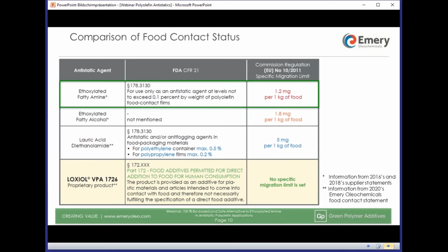An example. Let us assume you use 1 gram of packaging material to pack 1 kg of food, which is not much. Let us further assume you put 0.1% of ethoxylated fatty amine in the film, as allowed by FDA. Then you have 1 milligram of additive per 1 kg of food. If you assume worst case, which is full migration of additive from the film into the food, you are rather close to the EU limit already. So FDA and EU 10/2011 are pretty much in line here.